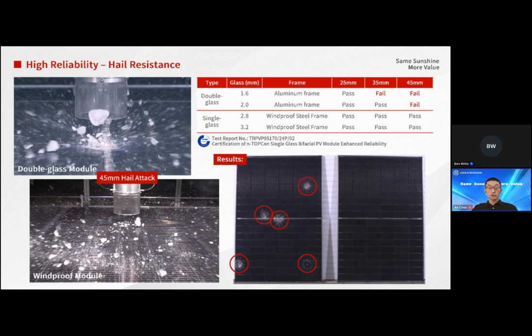Next, let's look at the hail resistance of the windproof module. We conducted a systematic hail test comparing the performance of the windproof module and the traditional double glass modules on different glass thicknesses and ice ball sizes. The windproof module's ability to withstand 45mm ice balls, even with thinner glass, underscores its exceptional durability and resistance to extreme weather. On the other hand, the double glass modules failed to pass the 45mm ice ball test, highlighting a key limitation when subject to large hail. This high level of performance, backed by rigorous testing, makes the windproof module a reliable choice for installation in regions prone to harsh weather events, ensuring long-term protection and efficiency.